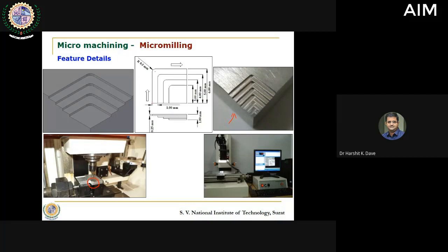We maintained the width of each step as 1 mm, and subsequently from 6 mm this size reduced to 3 mm. This is what we did. The total height of this feature was 1 mm, and each step that we generated is 250 microns. So though we used a regular desktop tabletop CNC milling machine and a 1 mm diameter cutting tool, we tried to produce features in the micro domain. Then we observed it under a vision measuring system to check the dimensional accuracy, and then check the quality of the surface generated with the help of that setup.